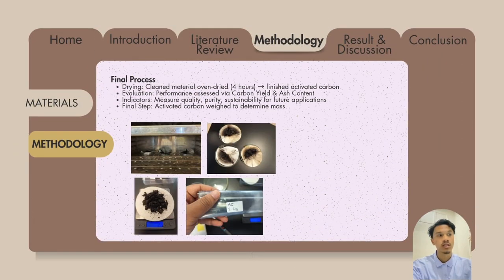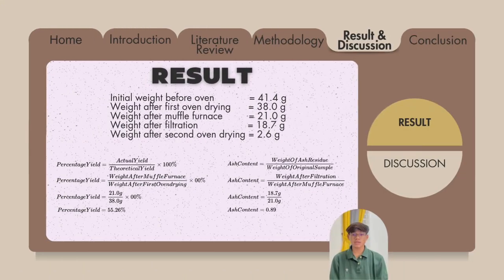For the final process, the clean material was oven dried for 4 hours, and then the final activated carbon obtained is weighed and evaluated by carbon yield and ash content as indicators of quality and purity. This is the result that we got from the analysis of the experiment, and we got the percentage yield and also the ash content by using these equations. For the percentage yield, we got 55.26% and also the ash content of 0.89.